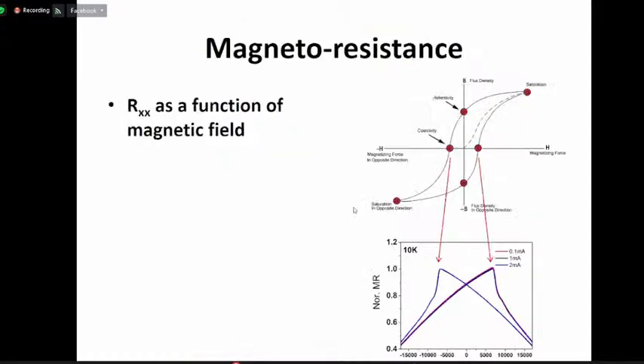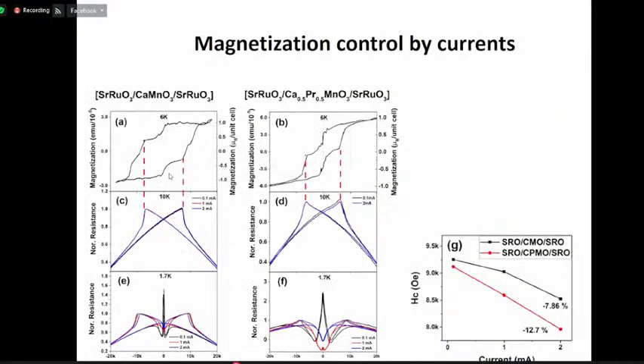Then, interestingly, we checked the magnetic hysteresis, but this film is very small, so we used resistance measurement. This is the magnetic hysteresis, then this is the resistivity, the butterfly shape. This peak corresponds to the coercive field. At 10 Kelvin, there is no dependence on the amplitude of the current, but at very low temperature, 1.7 Kelvin, the resistance depends on the current.